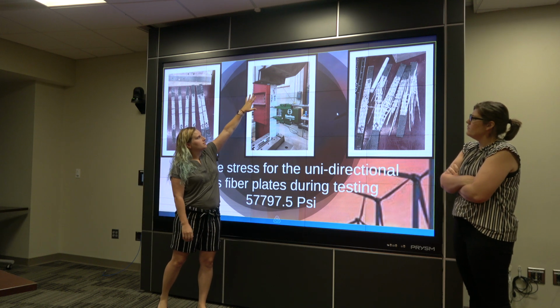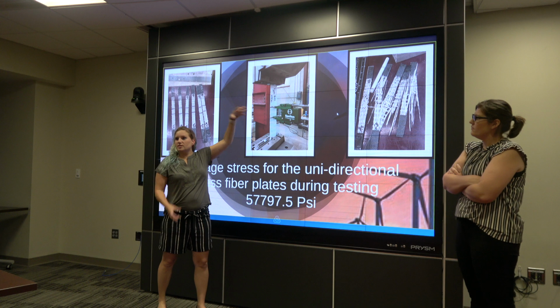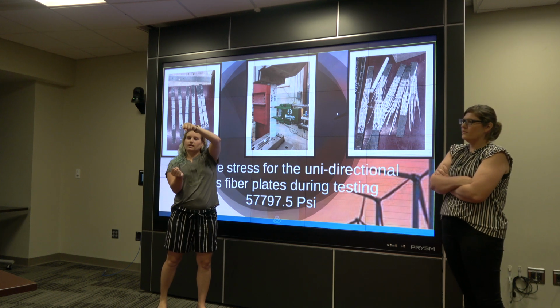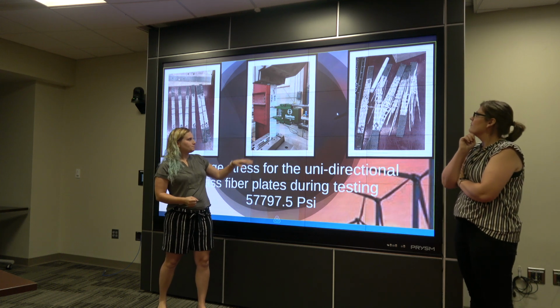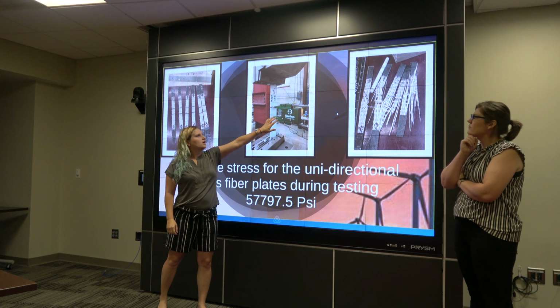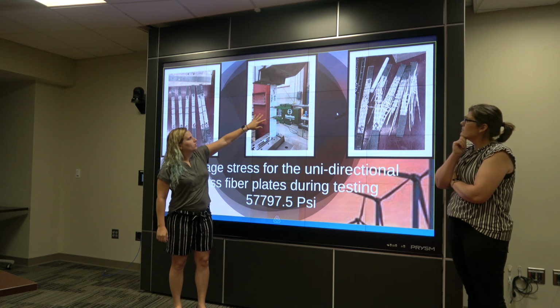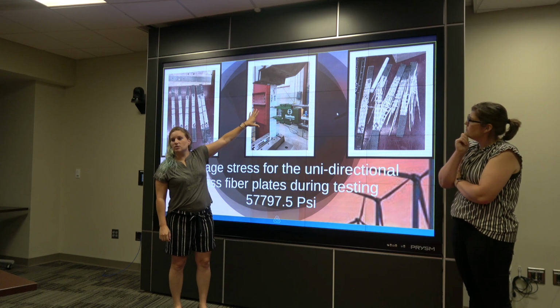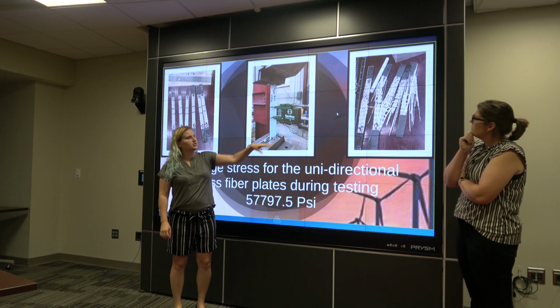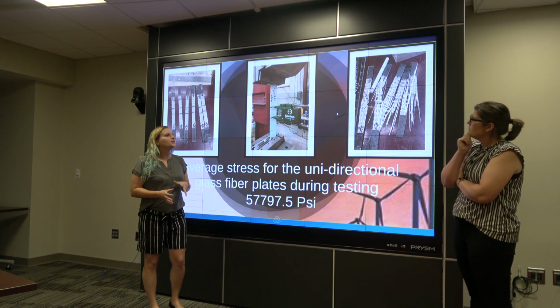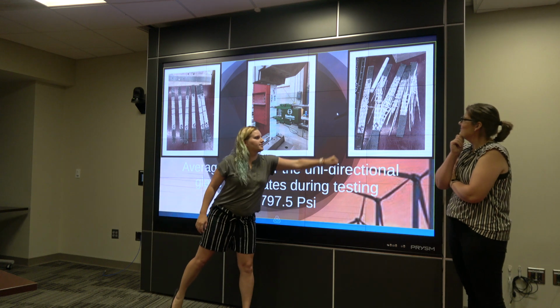And then we put this on here so that when we're in the machine, it's literally pulling at a rate of about 1 millimeter per minute, and then this is testing the displacement, and then once it gets to its point to start breaking, it starts cracking, and it makes this coolest sound, and this is what it ends up happening.